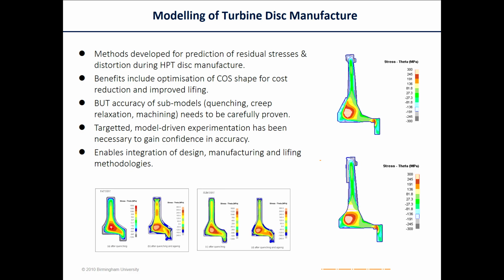Here's another example. We have turbine discs in the engine. Typically they are very heavy, maybe 100 kilograms in size. They're spinning around at maybe 10,000 revolutions per minute. Very big centrifugal stresses are set up. We have to machine these parts in a very intricate way from large pieces of metal. And you can see here that the residual stress fields, which are typically inherited from the quenching operations, have a habit of redistributing as the material is machined away.